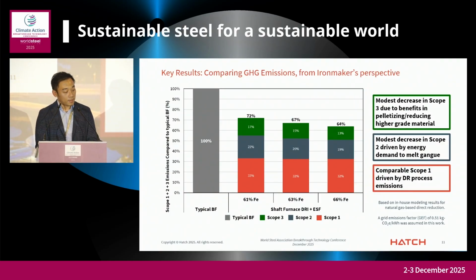I think the few key findings: the scope 1 emission is quite comparable, which is essentially your natural gas and so on. The scope 2, which is energy requirement, the electricity for the furnace, of course, the more you beneficiate, there's less slag, less gangue, so the emission does go down, but not by too much. And of course, scope 3, again, that's mostly from the pelletizing of the additional ore and so on. So there's also a decrease. The more you beneficiate, the less you have to pelletize, the less you have to melt. So there's a slight decrease in emission from beneficiating before going to ESF.